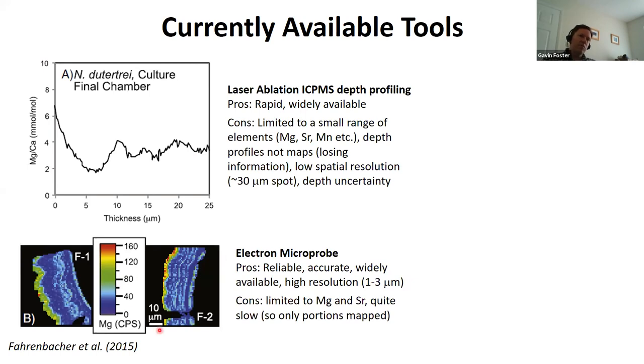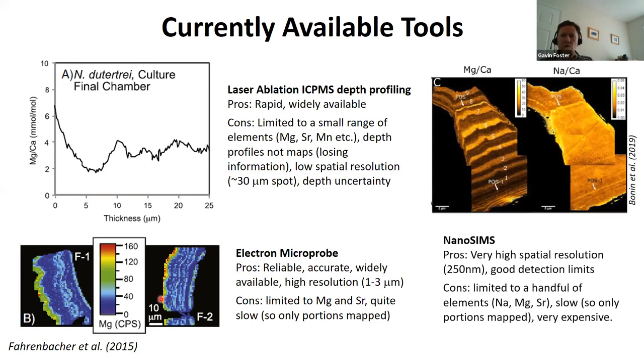So you only see sort of portions of the shell mapped in this way. So it'd be quite hard to get large numbers of shells mapped. And so a gold standard is NanoSIMS, very high spatial resolution, good detection limits. But again, you're limited to the number of elements that you can measure. It's quite slow, and it's very expensive, and actually access can be a little bit problematic to these big machines. So we turn to a new tool.